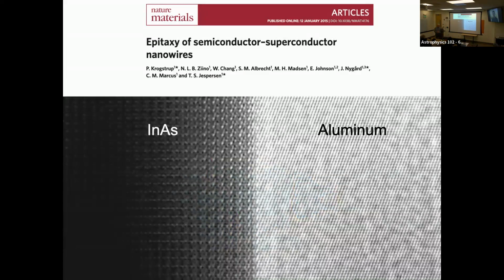We talked about this a little bit already, which was this material that got invented courtesy of some efforts in Copenhagen. This was just about the time that I was visiting on sabbatical, that these materials, two principal players in the story, indium arsenide, which actually has this negative work function, and aluminum, which superconducts, could be grown epitaxially. And that epitaxial interface was the magic to allow rapid transition of superconductivity into the semiconductor. The semiconductor could still be depleted, it still behaved like a semiconductor, you could make a field effect transistor out of it, all the magic of semiconductors, only now it would proximitize very effectively and become effectively super.